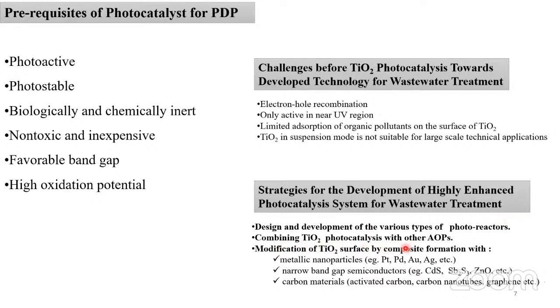Then combining TiO2 photocatalysts with other AOPs. And what we typically do when we work in the synthesis of photocatalytic nanomaterials is modify this TiO2 surface by composite formation or by formation of some heterostructures. In that, people are working, and I have worked a lot on the modification of TiO2 with metals such as platinum, palladium, silver, etc. Then they are preparing some heterostructures with narrow band gap semiconductors like CdS, Sb2S3, ZnO, etc. Because narrow band gap semiconductors will be active in visible light. They act as sensitizers there.